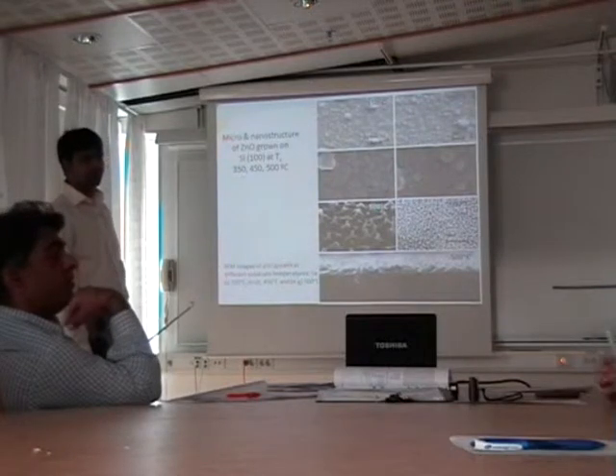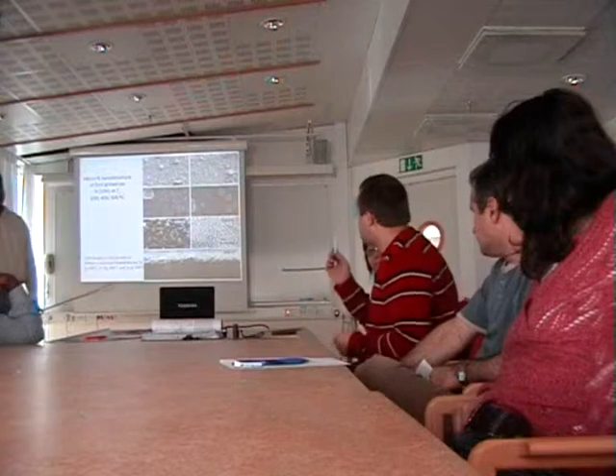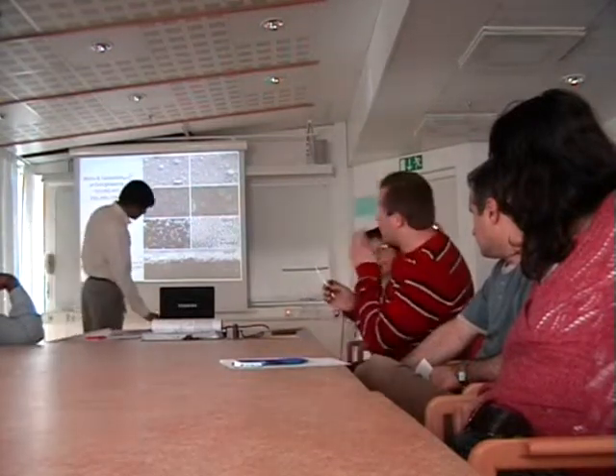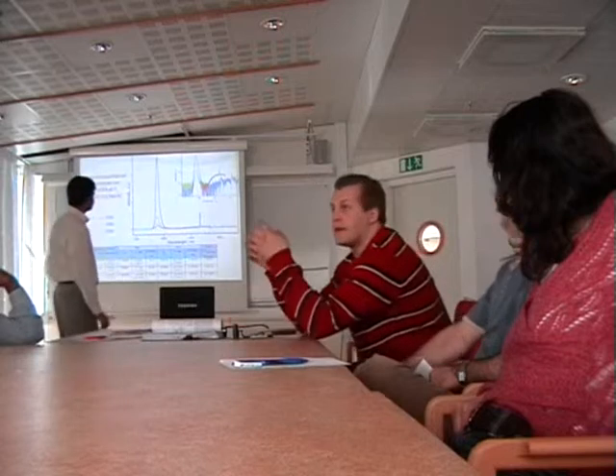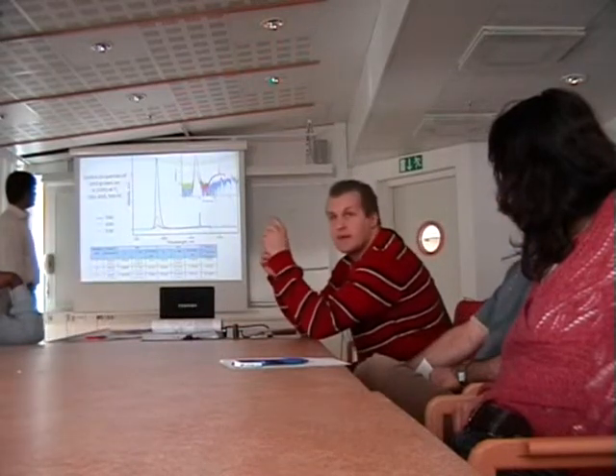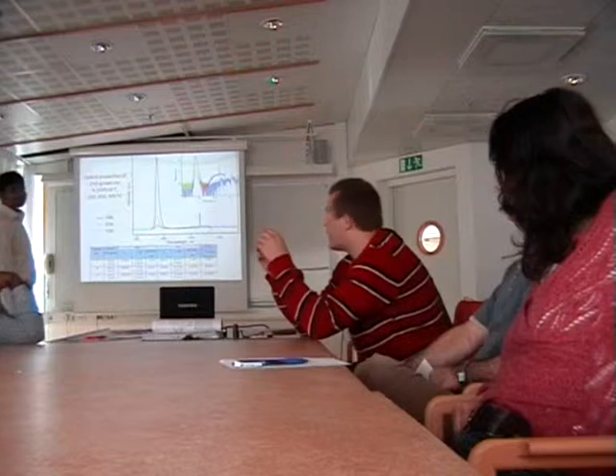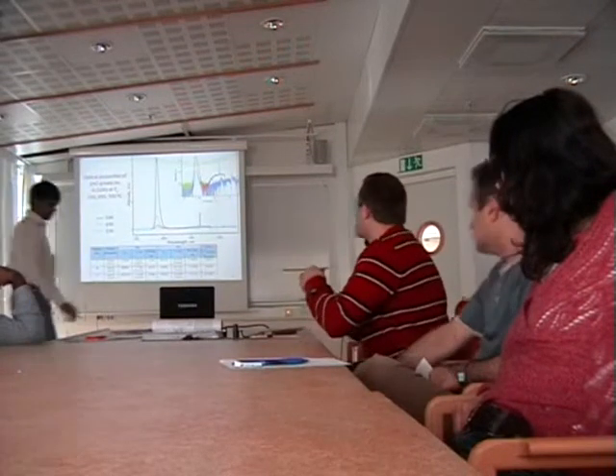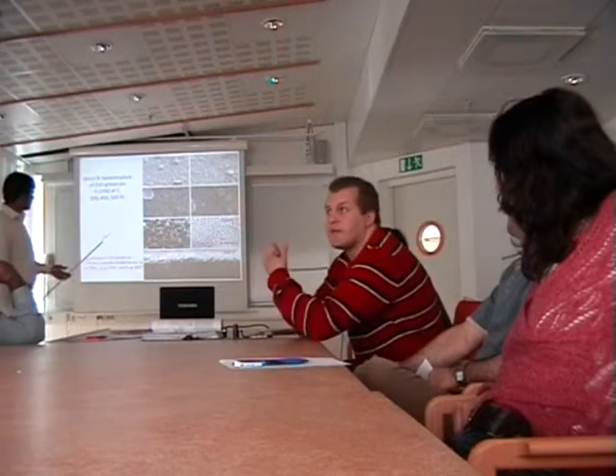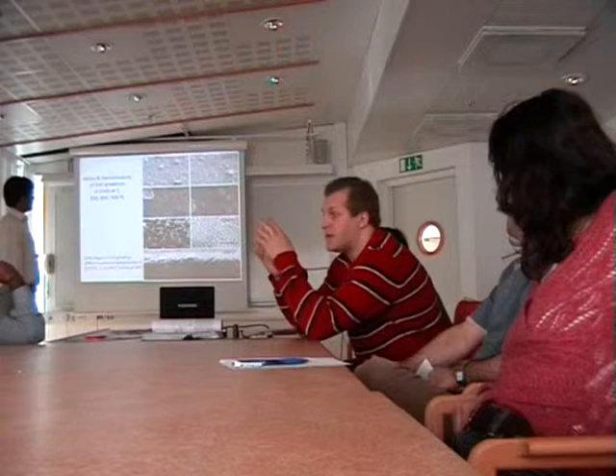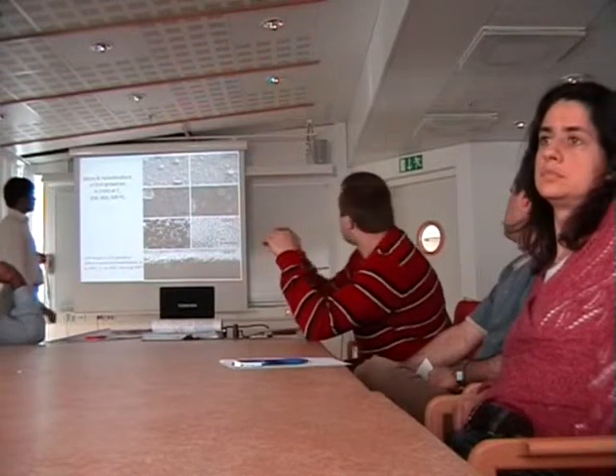Can I add? Actually, we can say that at higher growth temperature we have bad structural quality. If you look more carefully, in fact we have a summary signal from the nanopillars and this seed layer. Moreover, this seed layer, can you show it as a picture? It has special planes. There is a special mechanism for the formation of these nanopillars. So there is some XRD signal from these planes.